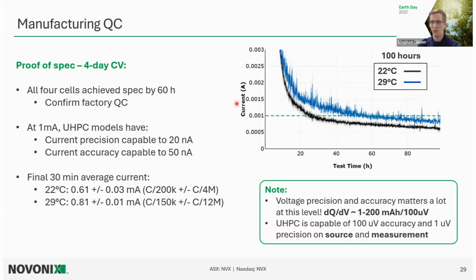And so using UHPC with pair cells at a couple different conditions, because in mass manufacturing, you may not be able to very consistently control the temperature of these massive facilities for QC. So this was the temperature range that we were given by industry. And you can see that pretty quickly, around 60 hours or so, we can measure very consistently between the cells that we tested. You can see the kind of shadow